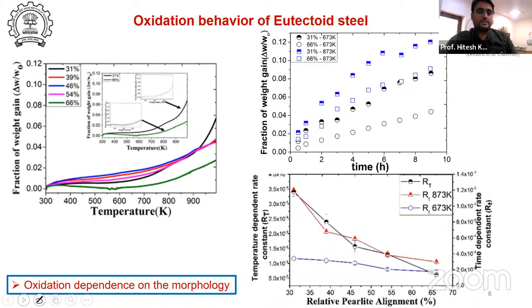Then these colonies are oxidized at different temperatures. One is the isochronal situation, when we heated the material from 300 Kelvin to 973 Kelvin, around 700 degrees Celsius, because at 723 the ferritic colonies are going to change again into the austenite phase. So we only chose till 973 Kelvin. So we can see the alignment of colonies affects the oxidation behavior. When we are aligning it more, the material gets more oxidation resistance, meaning the oxidation properties get enhanced.